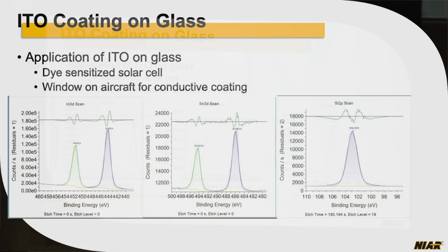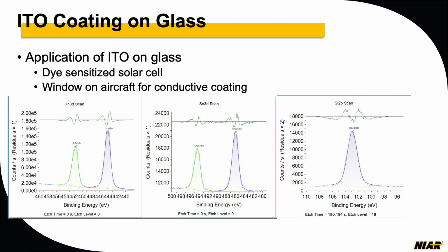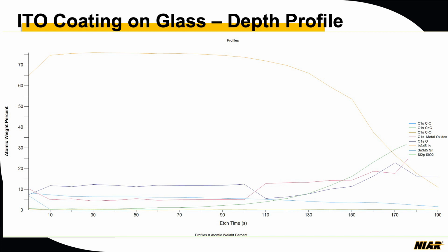So the next aspect, the whole idea was to identify silicon dioxide, to do a depth profile and see how the coating is affected. In this, your indium has the highest percentage, and as we go along in the etched profile, it has reduced after a very long etch process. And the tin, which is the blue, is consistent throughout and slowly degrades over time, but the percentage is somewhere around less than 10%. Now the silicon dioxide, which is almost zero, basically starts picking up. So this is the region where your coating system is starting to degrade and you're showing up the windshield material itself.